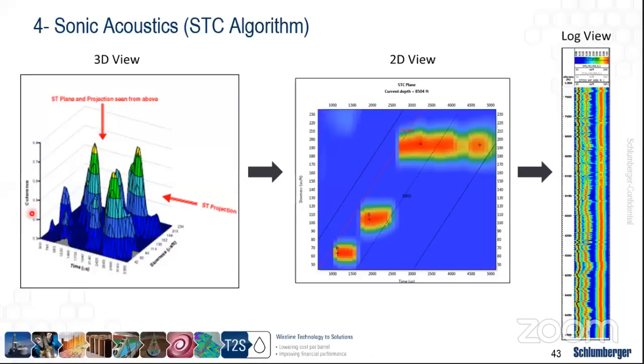STC stands for slowness time coherence, where we basically plot time versus coherence. Coherence is the data density, which is typically in red. The redder the color, the higher the confidence in the signal. The bluer the color, the less confidence that we have in the signal. So we plot coherence versus time and also versus slowness. As I said, in terms of time domain and slowness domain, we should be expecting compressional, shear, and then Stoneley later in time, and also later in terms of slowness.